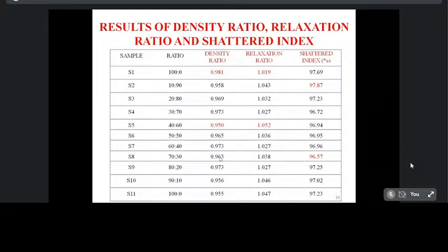Okay, so a relaxation ratio greater than 1 also indicates a good quality briquette. Here all the produced biomass briquettes have a relaxation ratio more than 1. So the minimum value achieved here is 1.019 for sample S1, ratio 100:0, and the maximum value achieved is 1.052 for the ratio 40:60, sample S5.